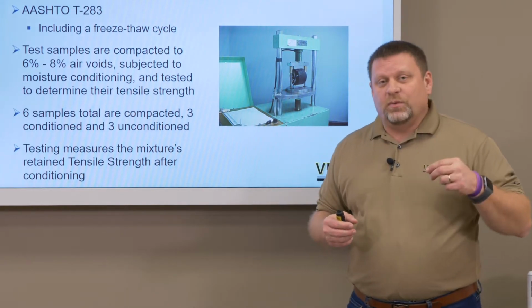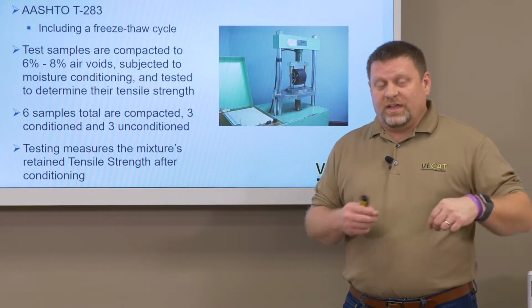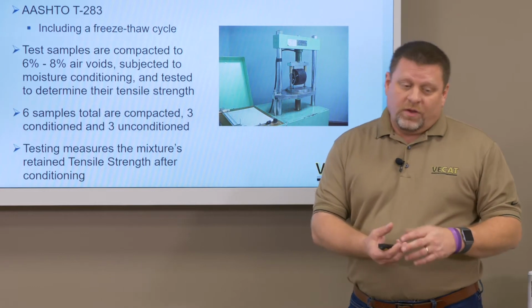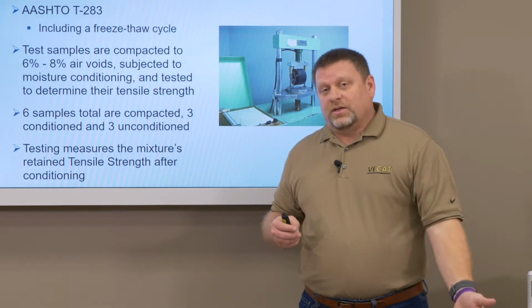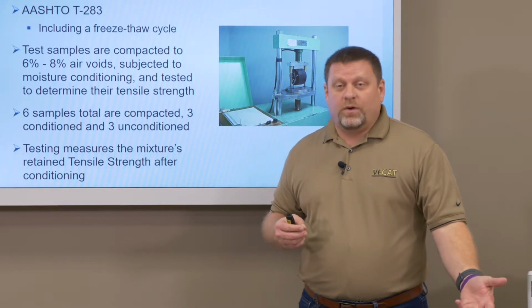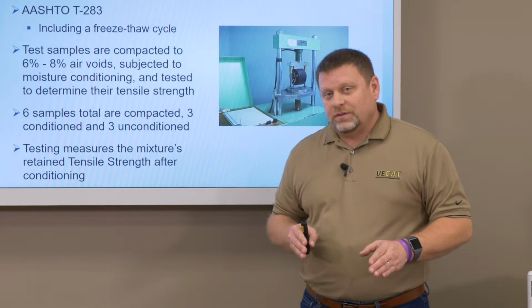I recommend, like you would dunk a donut in a cup of coffee, dump half of it in, it makes the plastic almost fall off, roll it over and do the other half, and the plastic just falls off your sample. You can lay your samples now in this hot bath at 140 degrees Fahrenheit. There they'll stay for 24 hours.